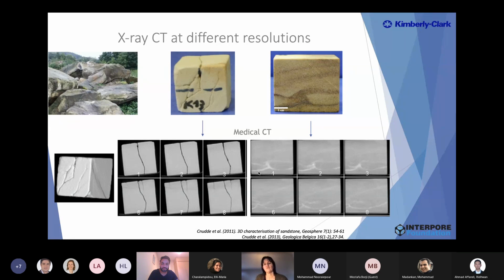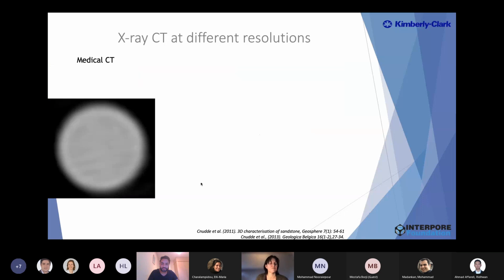One problem here: if you really want to understand the pore-scale processes, the resolution is not high enough. You can see this if you take a small sample, for instance one of 1 centimeter diameter. If you scan this with a medical scanner, you will not be able to see the individual grains or pores, because medical scanners typically have resolutions, depending on the system, in the order of 150, 200 micron. So if you want to visualize pores or grains in the order of several micrometers, you need higher resolution.